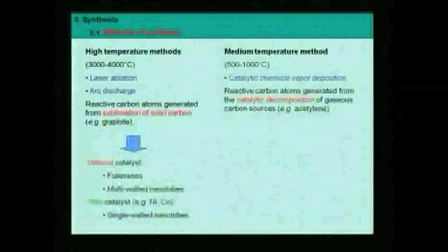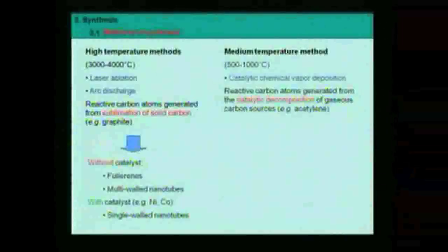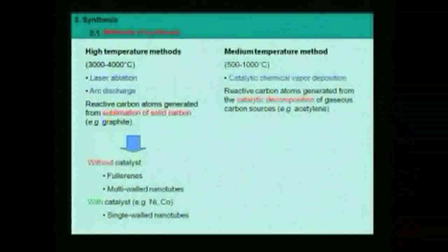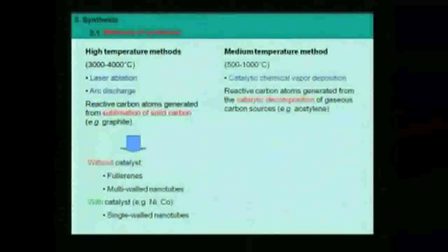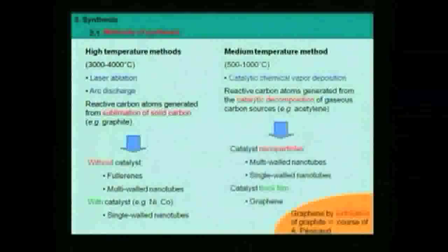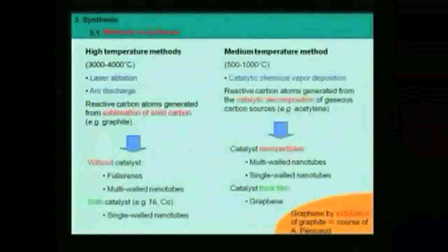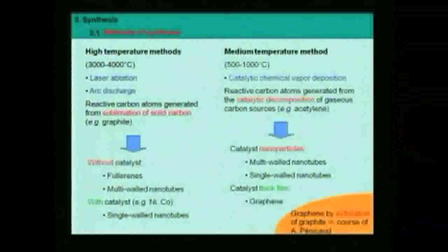The catalyst, as you already know quite well, allows to decrease the activation barrier for the reaction. It does not change the thermodynamics. It is just here the catalyst to make the kinetics faster by decreasing the activation barrier between the initial state and the final state. Okay, this is the purpose of a catalyst. And we will see that in detail. Once we have decomposed the carbon-bearing molecules, we got reactive carbon atoms. And the carbon atoms can coalesce at the surface of the catalyst, and they can make different type of materials.